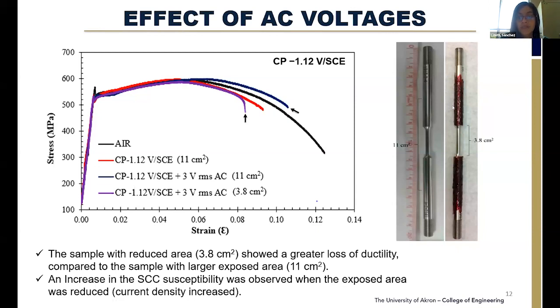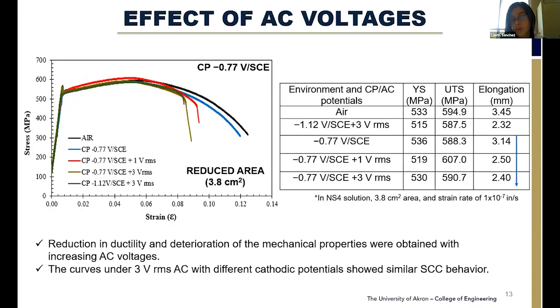So in this case, the purple curve that I show here is the one that shows the least elongation, the loss in ductility, compared, for example, with the sample only in air and with the sample even with a higher area, that is 11 square centimeters. So we see the increase in the cracking susceptibility is because we have an increase in the current density going to the sample with a decrease in the area. After that, we ran a test with the cathodic potential that was minus 0.77, but in this case, all with the reduced area.